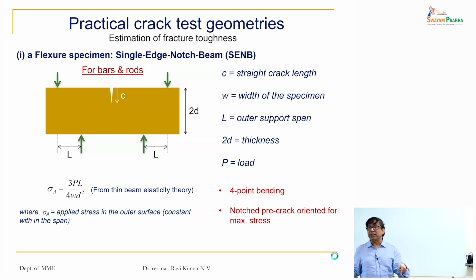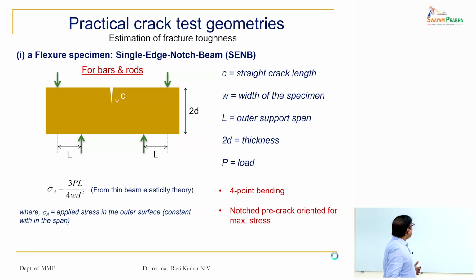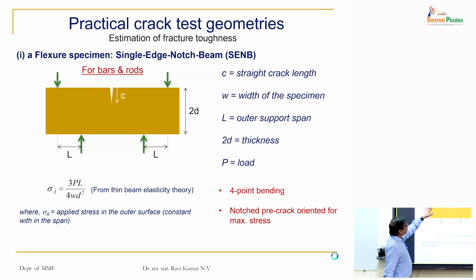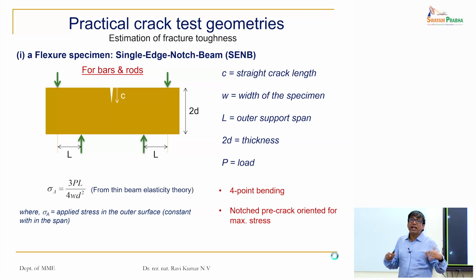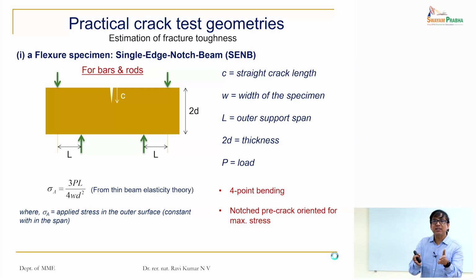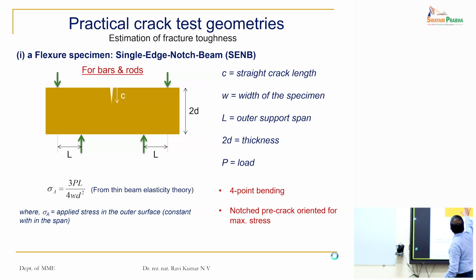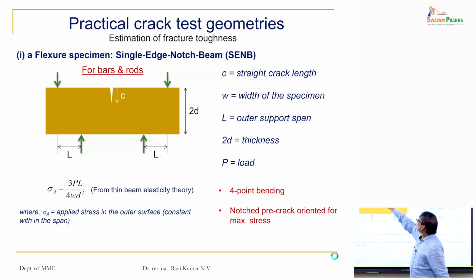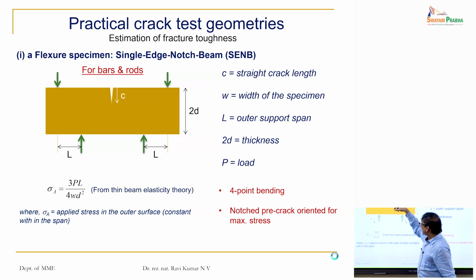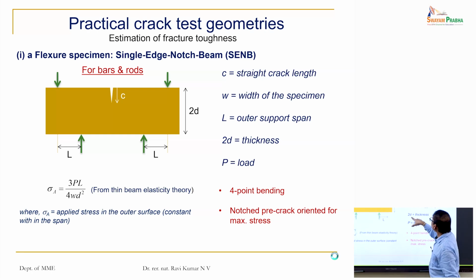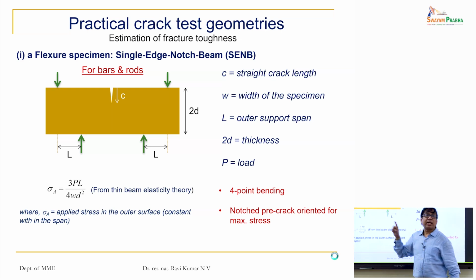But for that, you need to quantify it, and quantification requires a methodology. One of the important methodologies is called the single edge notch beam. Basically, you have to test the sample like in 4-point bending. That is why I said if you have a 4-point bend setup, you can measure not only the 4-point bend strength but also the fracture toughness. If you don't have a crack, you get the 4-point bend strength. If you introduce a crack as per standard, and then apply load to the extent that the crack is going to extend, then you know the load at which the crack is going to extend. That will be the critical load. L is this length and W is the width. D is half the thickness, and that will give you the critical failure stress.